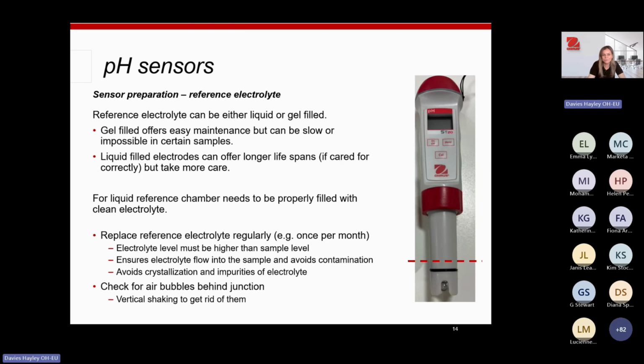Sensor preparation, so the reference electrolyte. I'll scoot over this quite quickly because it may not really relate if we've got a combined electrode that is not refillable with the reference electrolyte. But you can have reference electrolyte that is either liquid or gel filled. Gel filled ones are easy to maintain, but they can be a bit slow and a little bit impossible in certain tricky samples. But for general aqueous solutions, they should be absolutely fine. You can get liquid filled electrodes that do offer longer lifespans, only if you care for them correctly, and they do take a bit more looking after.